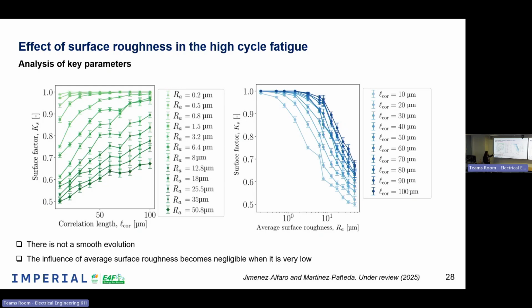First of all, you can see that there's not a smooth evolution of this. This is because we have random distributions. So you can see here the different margin errors that we have for each point, and this is why we have those peaks. And moreover, the influence in the surface factor becomes negligible for very low values of the average surface roughness, as you can see here, because it's like a straight line.